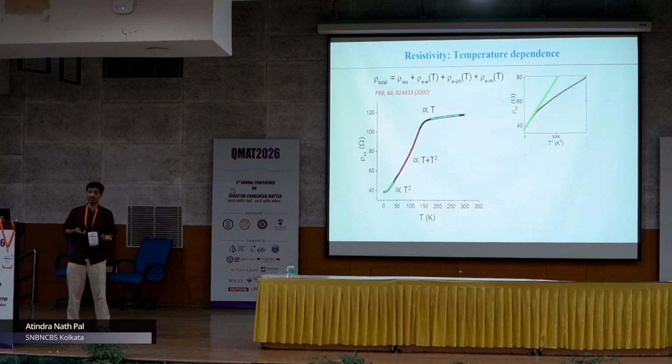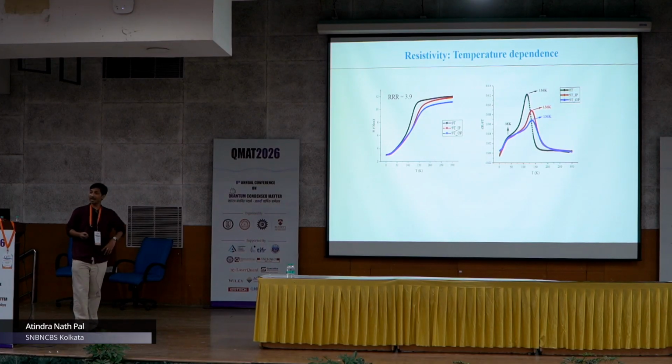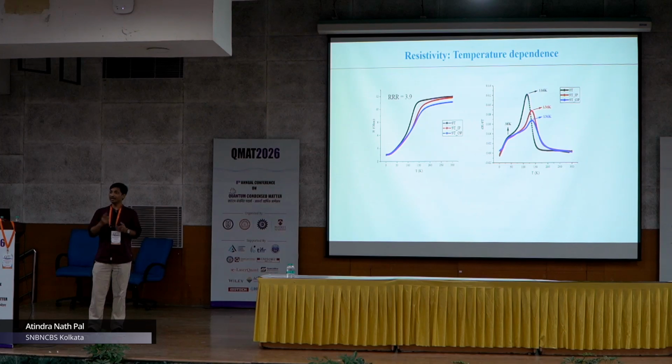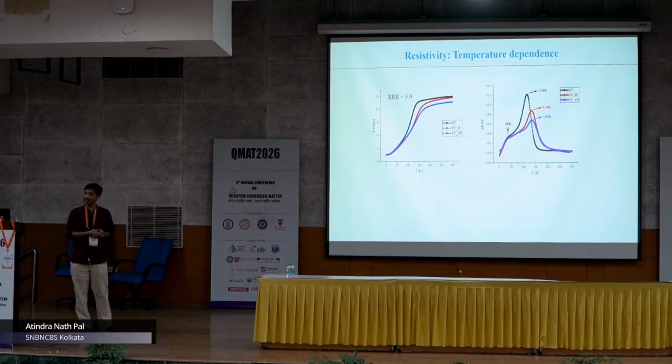So how to decouple this? This is verified in other devices also. What we have done is we have applied a magnetic field. Electron-electron and electron-magnon interaction you can decouple by applying a magnetic field. Electron-electron interaction typically should not change with magnetic field. If it is electron-magnon, then it will be suppressed by the magnetic field.